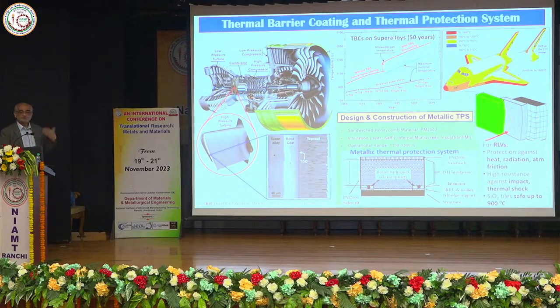But they are exposed to 1050 degrees or above, so they are prone to high temperature oxidation, creep, and other thermal fatigue damages. So there's always a lot of research happening to improve further, because if you can rotate at higher speed and withstand higher temperature, your thrust to fuel ratio increases, and instead of 10 hours you can fly continuously for maybe 20 hours. So obviously that's a big difference.